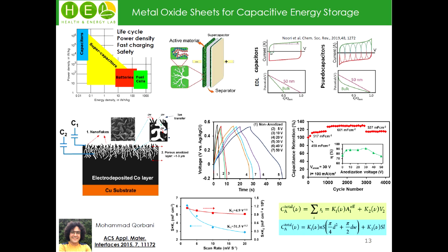In this project, we electrodeposited a thick layer of cobalt and then tried to anodize the layer to produce a porous film, and at the same time, because of the anodization reaction, some flakes formed on the surface of the porosities. So we had two layers in junction with each other by one-step anodization, and we found the optimum voltage for such an anodization process, and found that we should have an activation process, as you can see here, after nearly 1,000 cycles running such devices.